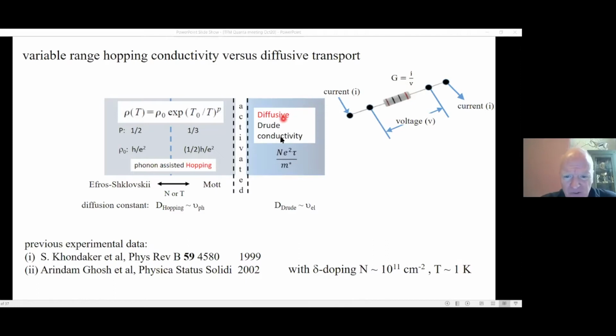So what happens in a doped semiconductor at high temperatures, say an extrinsic semiconductor at high temperatures? We describe the system as diffusive. Diffusion in semiconductors is one of the basics that we learn as an undergraduate. We learn about p-n junctions. To understand a p-n junction, we look at how the charge diffuses and drifts across the interface. It's very, very important to understanding transport in semiconductors. You can describe the conductivity as n e² τ over m*. Any temperature dependence comes from a temperature dependence of n, or τ, which is the momentum scattering time.